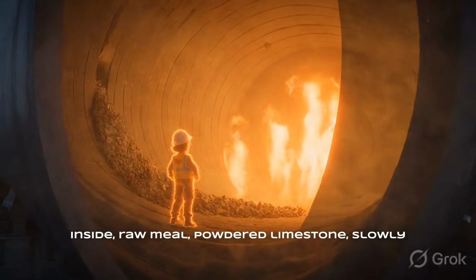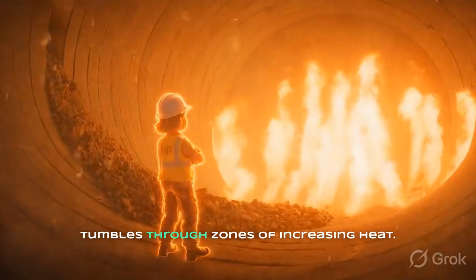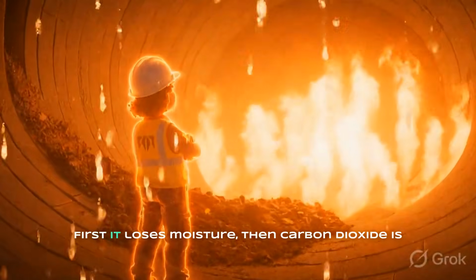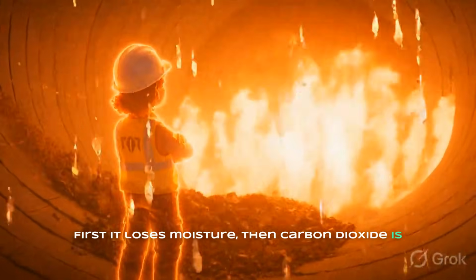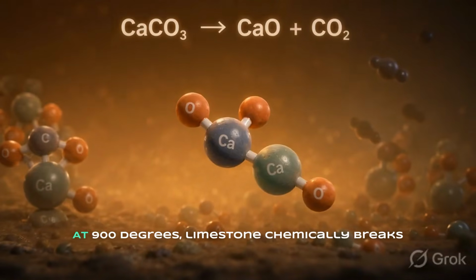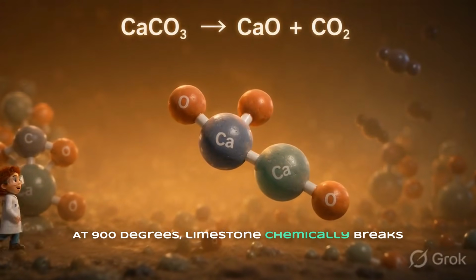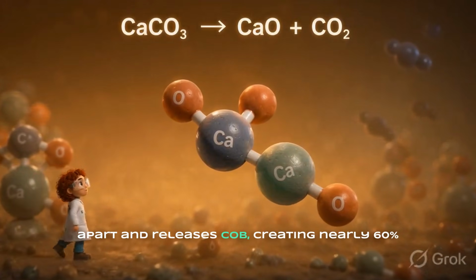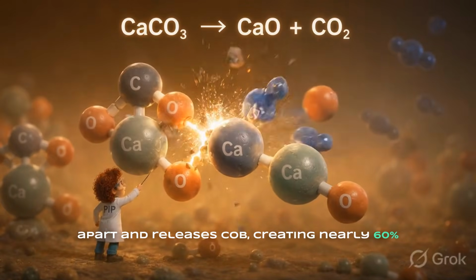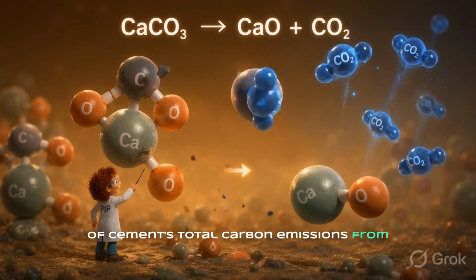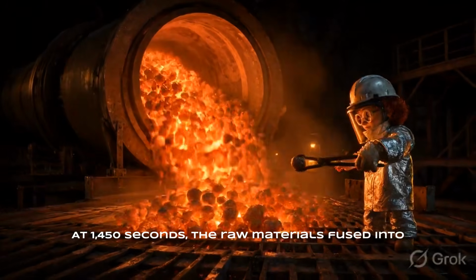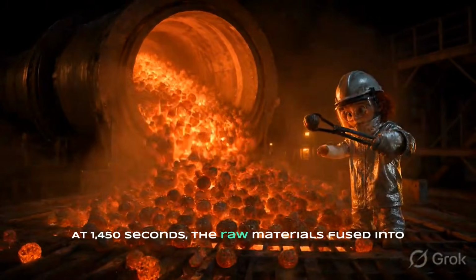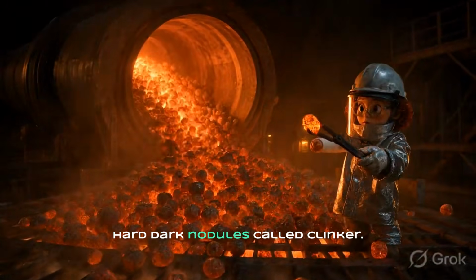Inside, raw meal, powdered limestone, slowly tumbles through zones of increasing heat. First it loses moisture, then carbon dioxide is driven off in calcination. At 900 degrees Celsius, limestone chemically breaks apart and releases CO2, creating nearly 60% of cement's total carbon emissions from cement production. At 1,450 Celsius, the raw materials fuse into hard, dark nodules called clinker.